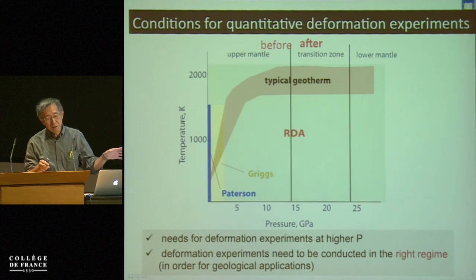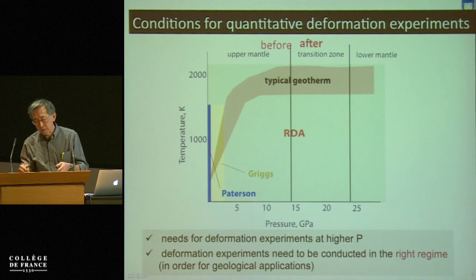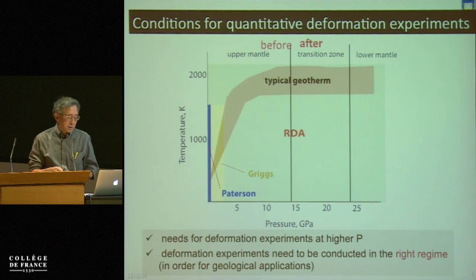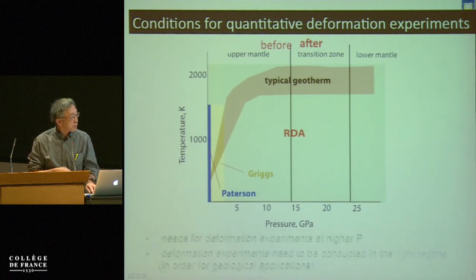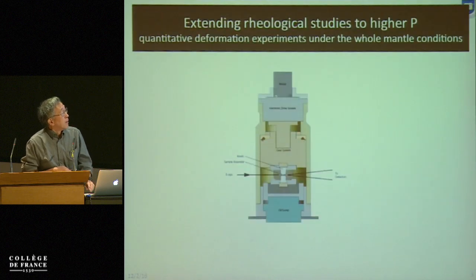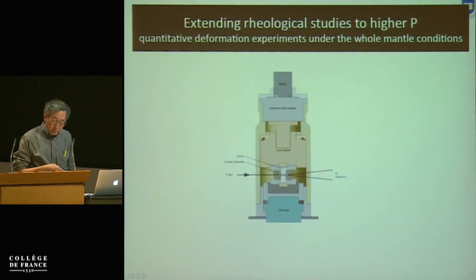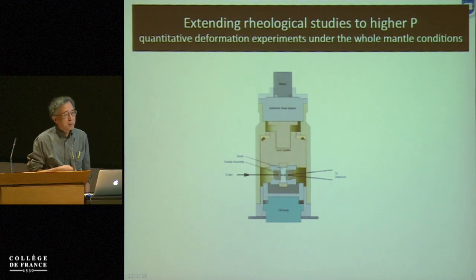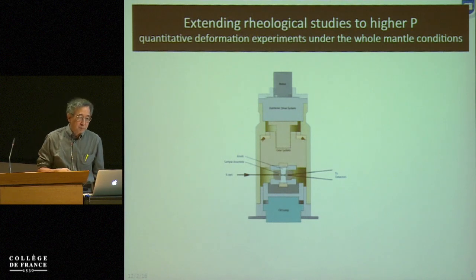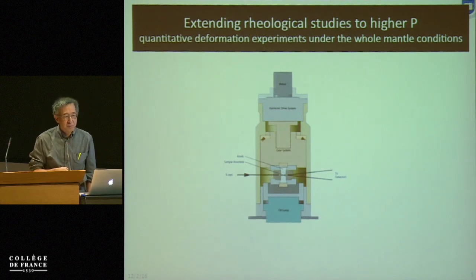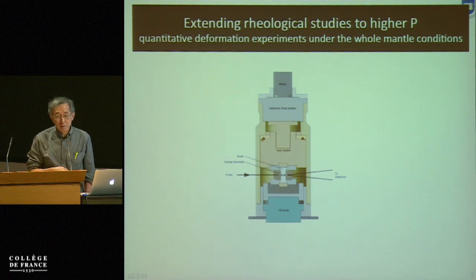Because if the mechanisms are very different between lab and Earth, you cannot extrapolate those results. That's a really challenging issue, very specific to studies on plastic deformation. And so to extend the pressure and temperature conditions, you really need to design new apparatus. If you have money, you can purchase apparatus, but those apparatus work only to 0.3 GPa. So I extended 0.3 to 30, so 100 times higher pressure.